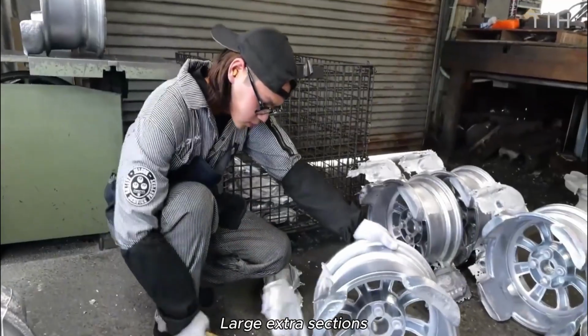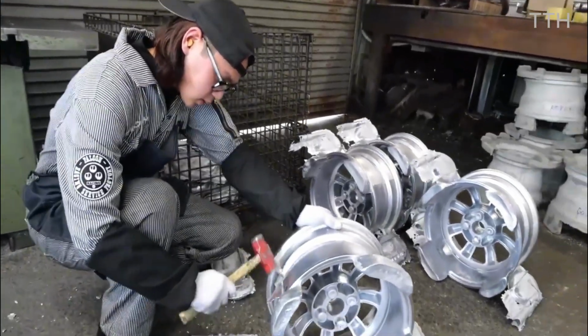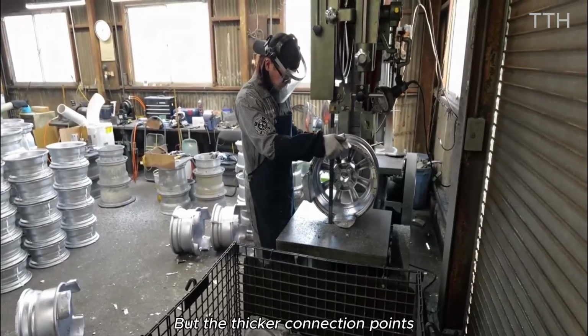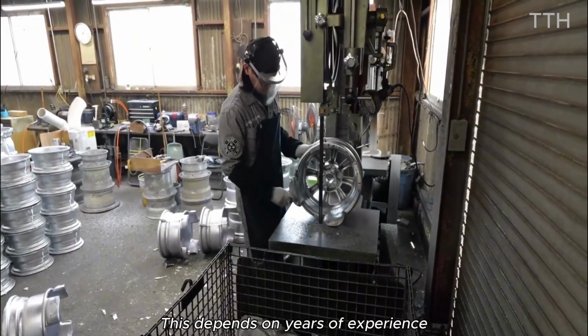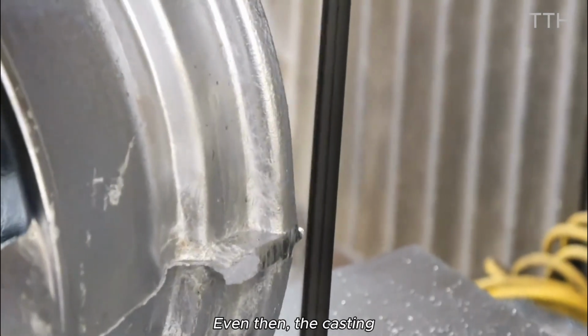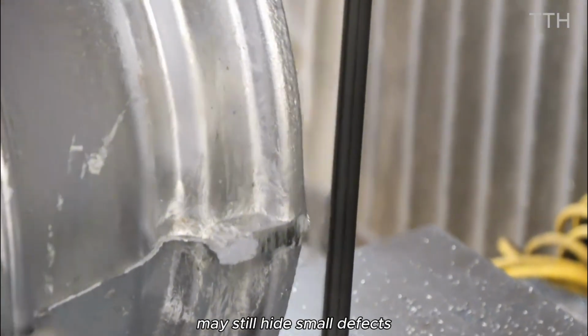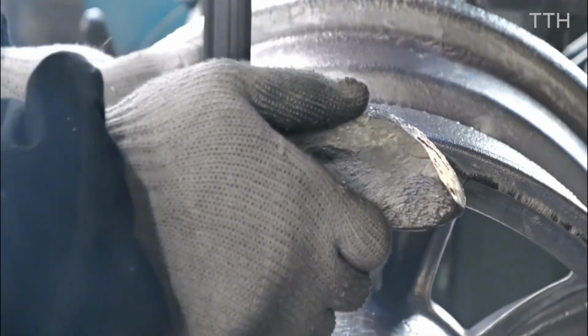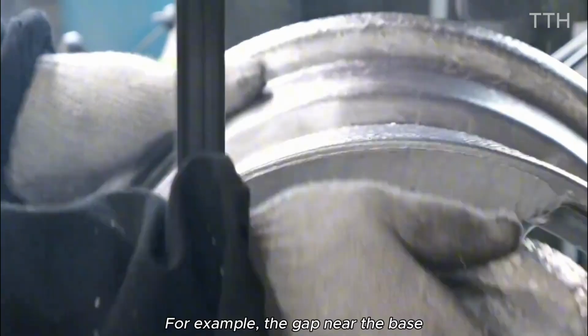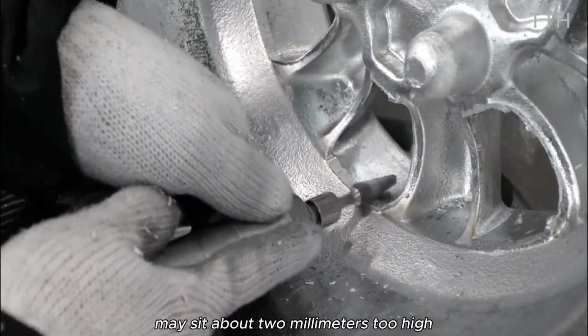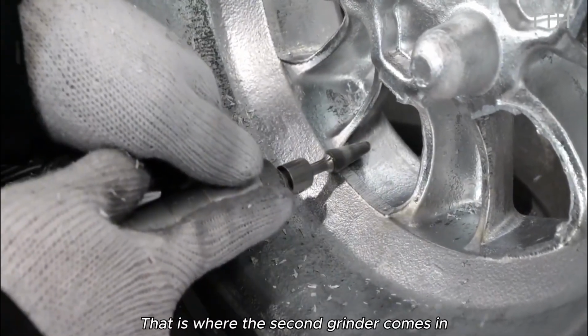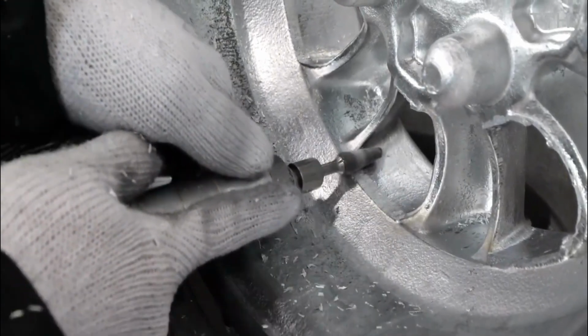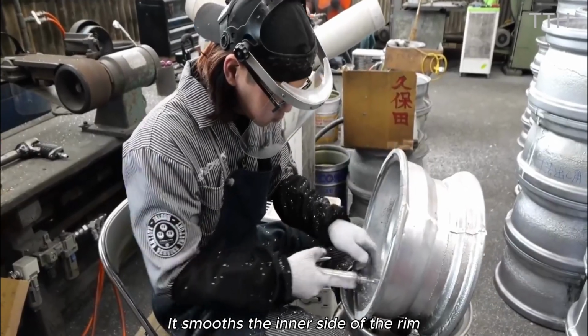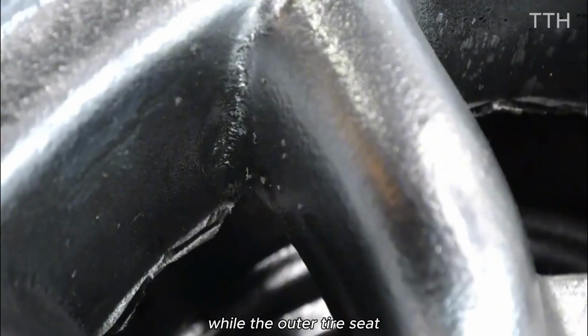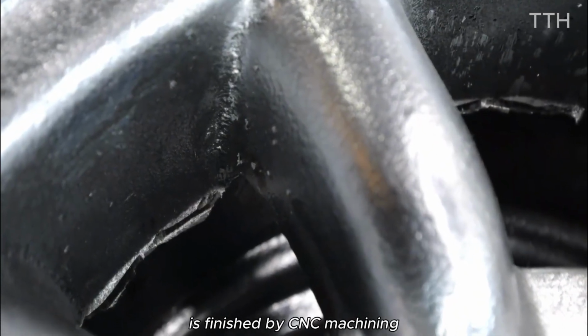Large extra sections break away with a light tap, but the thicker connection points need a power saw. This depends on years of experience. Even then, the casting may still hide small defects. For example, the gap near the base may sit about 2 millimeters too high. That is where the second grinder comes in. It smooths the inner side of the rim, while the outer tire seat is finished by CNC machining.